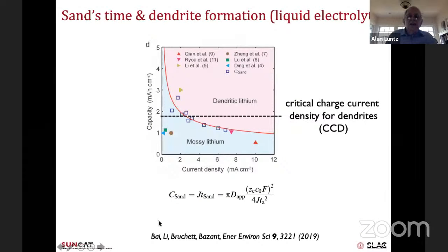And there's been some very nice work. It turns out that if you look at how much capacity you have in the battery, or how much lithium you're trying to plate out, versus current density, there seems to be a very sharp dividing line between the two. So if you stay in this regime, you can have a more or less stable battery with perhaps a lower coulombic efficiency. But if you're in this regime, you have a very unsafe battery. So there's sort of a critical current density for forming these dendrites.